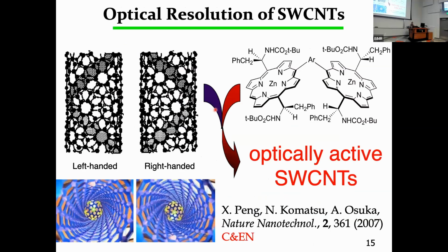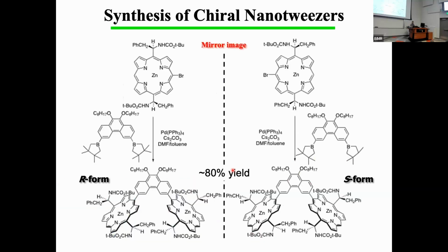Okay, so here are the actual results we obtained. This is the first paper we published on carbon nanotube separation based on host-guest chemistry. As I told you, we put the stereogenic center at the periphery of the porphyrin unit, and this successfully recognizes the left-handed and right-handed structures. We independently applied the R structure and the S structure of these nanotweezers, and we successfully separated the left-handed and right-handed structures of the carbon nanotube.